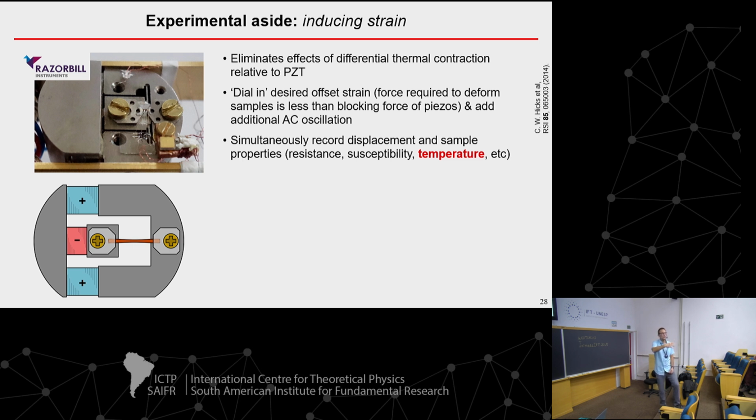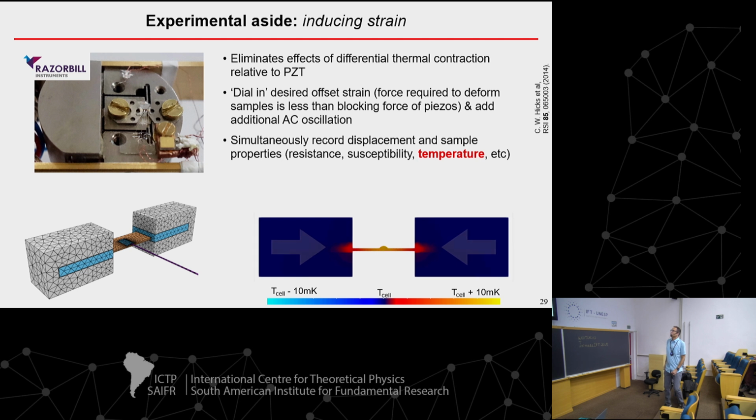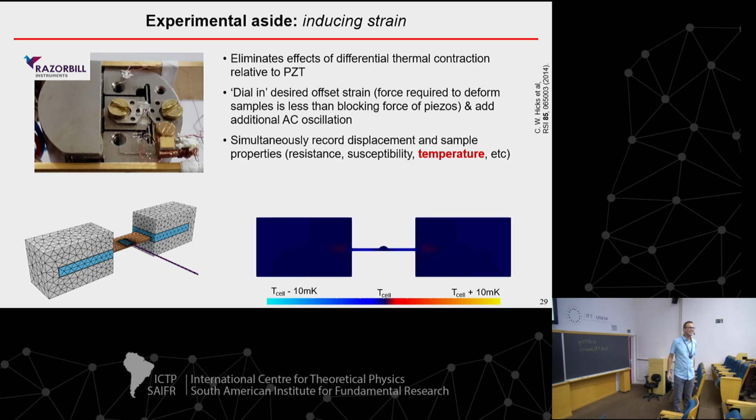And I think we had a question in Elena's talk about how you are going to guarantee this is adiabatic, or at least quasi-adiabatic. So you have to do this at a frequency which is higher than whatever the characteristic thermal relaxation rate, or 1 over that, is. And you can do adiabatic decompression measurements. You can do a DC version, just release the strain and actually measure the thermal relaxation and even confirm that you're in that regime. Yeah, exactly. That depends on the material. For the materials that we look at in the temperature regime that we look at, it's tens to hundreds of hertz.